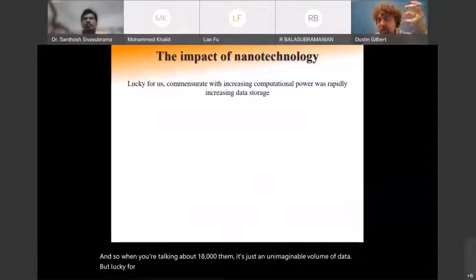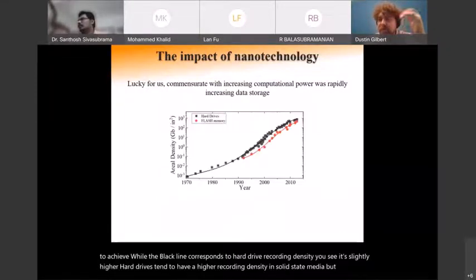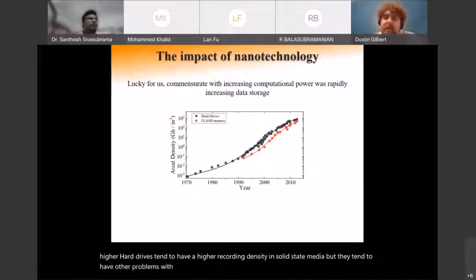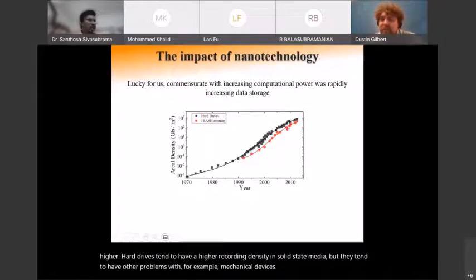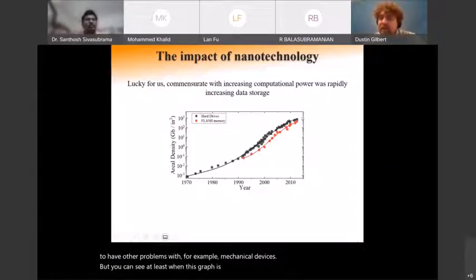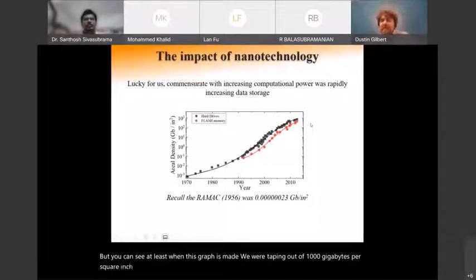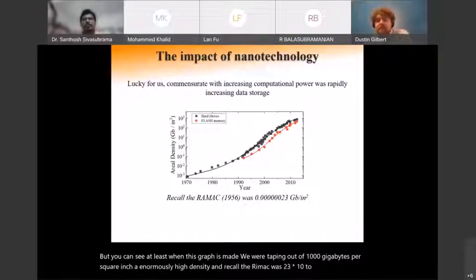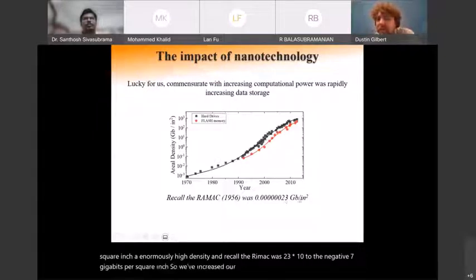Hard drives tend to have a higher recording density than solid state media, but they tend to have other problems, for example, with mechanical devices. But you can see, at least when this graph was made, we were topping out at about 1,000 gigabits per square inch, an enormously high density. Recall the RAMAC was 2.3 times 10 to the negative 7 gigabits per square inch. So we've increased our data storage capacity by 10 to the 10 over this time frame.